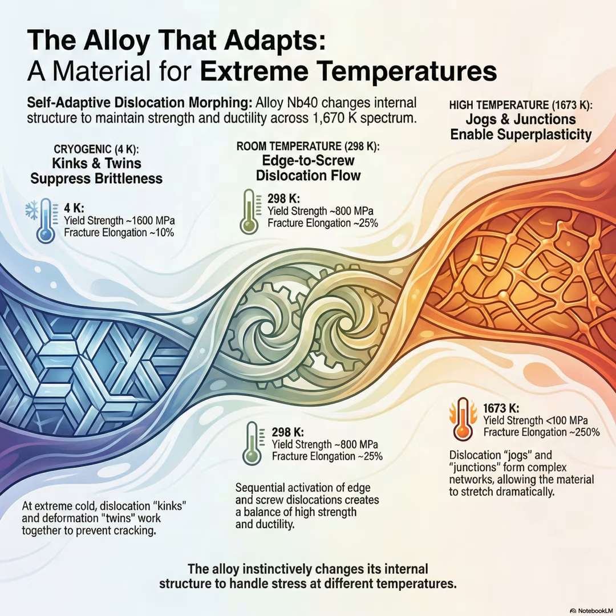You don't. And the critical insight from their X-ray diffraction work was that this isn't happening because the material is changing its chemistry or its basic crystal structure. It stays as a single-phase BCC structure the whole time. The secret is all mechanical. It's about how these tiny atomic-level defects inside the crystal manage the stress.